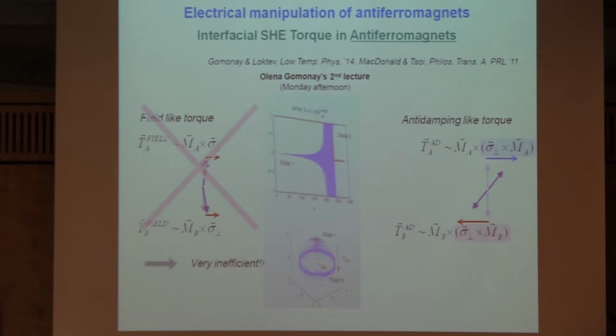You would start to get a kind of precessional motion of your L vector, and then it would depend very crucially on when you stop your pulse. And it would also not only depend on the pulse length, it would depend on the damping. Because you have some inertia, your magnetization, or your L vector, would start to precess further. So you would, in principle, have no way to really deterministically switch the antiferromagnet with this anti-damping torque.